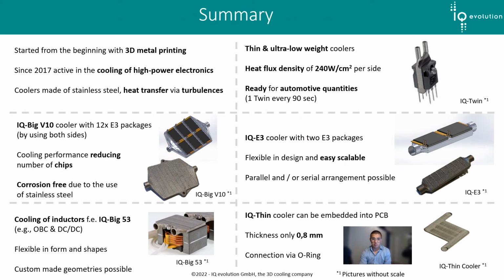And finally, as a summary, we use stainless steel as a material for our 3D printed liquid coolers. Since the coolers use turbulences as a heat transfer, the thermal conductivity doesn't matter. We have printed microcoolers for discrete semiconductors, for example the IQ Twin. The twin in high volume will be manufactured every 90 seconds and has a heat flux density of more than 240 watts per square centimeter with 50-50 water-glycol mix.